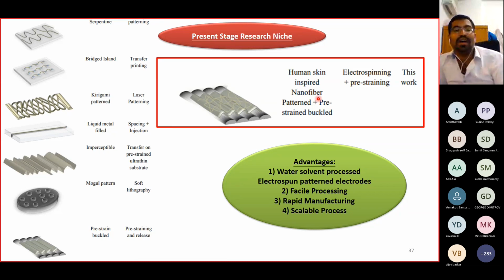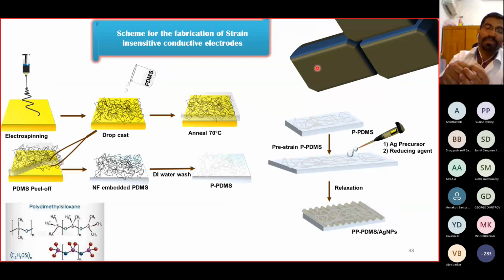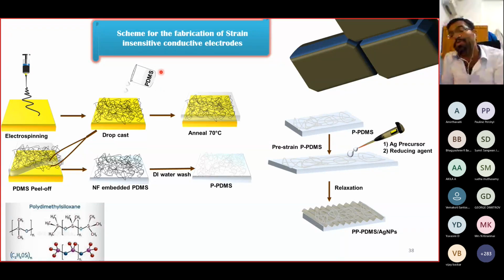And here I'm going to show a different pattern called a nanofiber plus micro wrinkle structure. This is similar to our human skin. I start with another electrospinning process to form some nanofibers, and then I use some PDMS elastomer and anneal, then peel and wash them. Then you get some nano crevices there, because all the nanofibers are etched out on the surface. The others are going to reinforce your polymers.